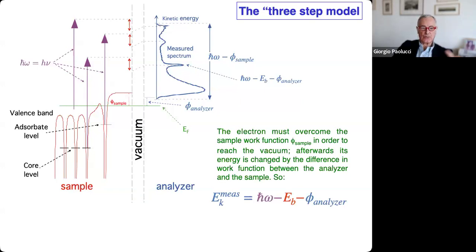So the energy you measure is, to a first approximation, assuming that the electron states are not changed by the phenomenon itself, which is of course an approximation, not completely true. But to a first approximation, one can say that you measure the binding energy by this formula. So you subtract the binding energy from the photon energy, and then there is a constant which is due to the instrument we're using.